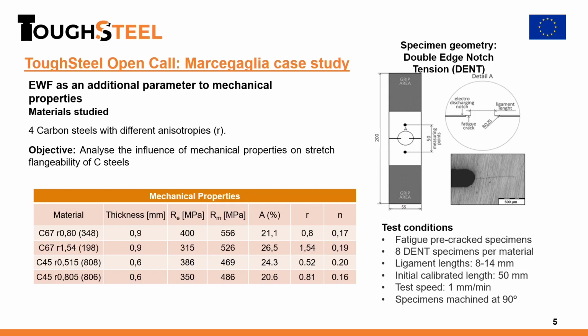In this case, we have 2 groups of materials. One was C67 and the other C45 with different anisotropy values. And we performed the test, as we explained before, with the essential work of fracture method, with double edge notch tension specimens, and we get the fracture values as we have done for the previous results.